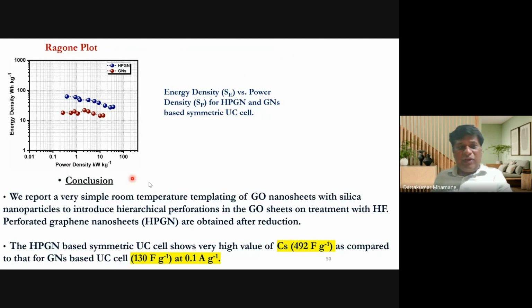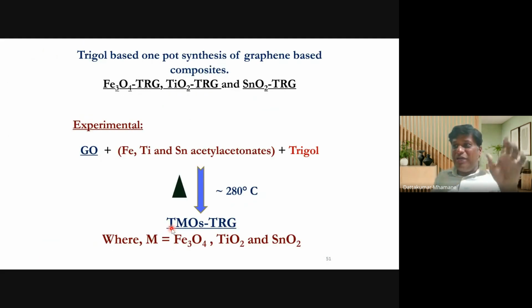So this is a Ragone plot. It's okay. So what I'm trying to tell all of you, we achieved a capacitance of around 500 in the case of perforated graphene, but in the case of non-perforated graphene, we achieved only 130 farad per gram. So one challenge we accepted and we did that. So another challenge, it is very difficult to prepare.